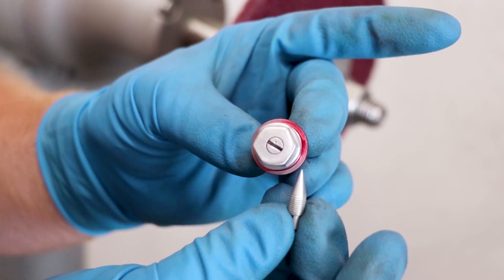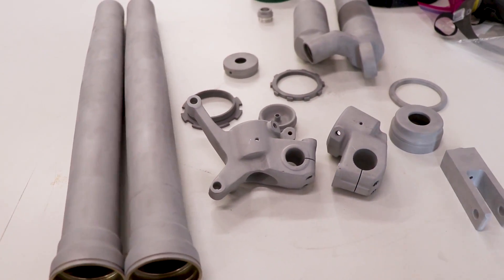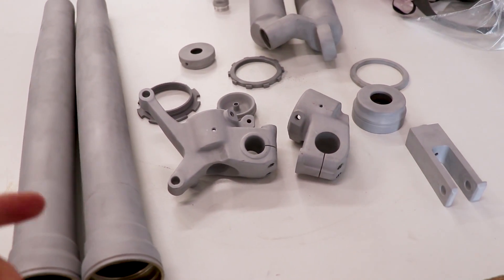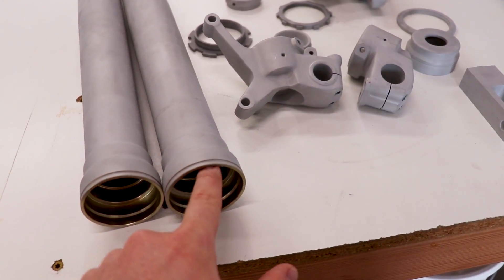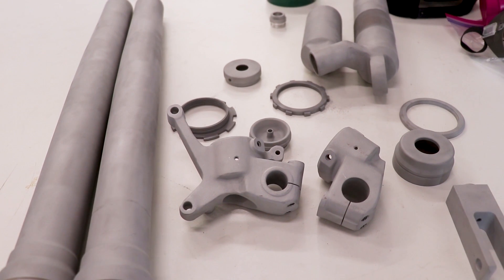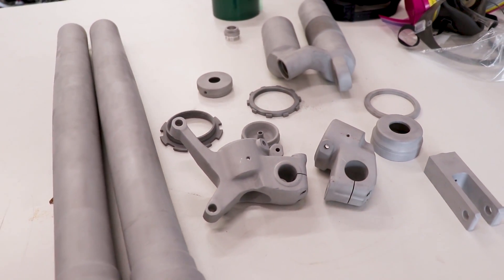After a little buffing, I'd say it turned out pretty good. Let's get back to some Cerakote prep now. Now that I've got everything bead blasted, the next steps are to clean this stuff up with Dawn dish soap, then soak it in acetone and mask off some of these inner surfaces once again, then bake it through the oven to burn off any remaining contaminants, and then we can finally get to spraying the Cerakote.